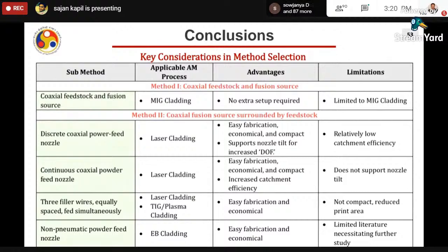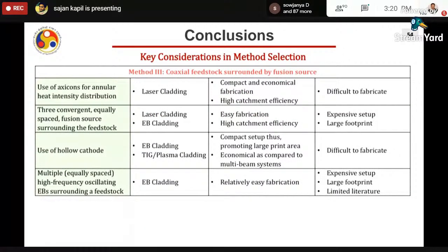We'll see. Then method 3 is coaxial feedstock with fusion source, in which the center will be the feedstock and from the surrounding the fusion source will come. We have seen in laser cladding that it can be achieved, but manipulating the shape of the laser is a bit difficult task. Only experts can do that. Laser cladding and electron beam cladding with 3 beams, yes, that is easy. You can easily mount 3 guns. Like I said, a few Chinese systems are also there. They need not have expertise in the laser. Just buy 3 systems, mount 3 lasers at an angle of 120 degrees and do the job.